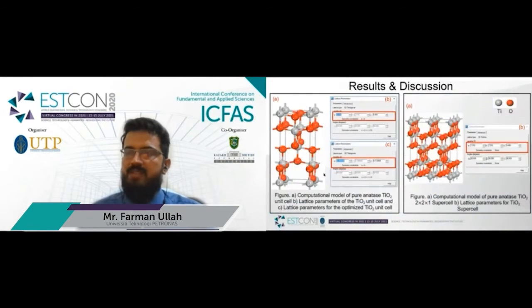For results and discussion, on the left side in figure A, the computationally designed model for pure anatase TiO2 is shown. Figure B represents the lattice parameter of the TiO2 unit cell, and figure C represents the lattice parameter for the optimized TiO2 unit cell. On the right side, we designed a 2x2x1 supercell model for anatase TiO2 along with lattice parameters for this supercell.